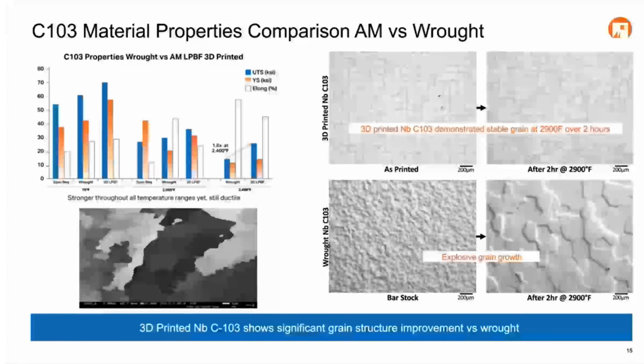And so we get a microstructure that is going to be very refined, resulting from that rapid solidification. And then we also get formation of these very fine secondary phases, such as hafnium carbides and hafnium oxides, at very fine length scales - tens, hundreds of nanometers, both at the grain boundaries as well as, you can see here in the lower left-hand corner in this SEM image, dispersed throughout the grains, and the grains themselves are in the order of tens of microns in size and in either orientation.